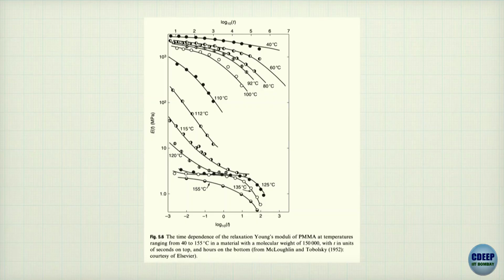One is, as temperature is increasing, the moduli are decreasing in general, right. So you are going from about 10 to the power 3 megapascal to about 1 megapascal at 155 degrees Celsius, right. Somewhere in between there is a temperature range where the decrease in moduli is the highest. Can you see what is that range in temperature where the moduli has decreased the most? Around 110, 100 degrees Celsius, right.